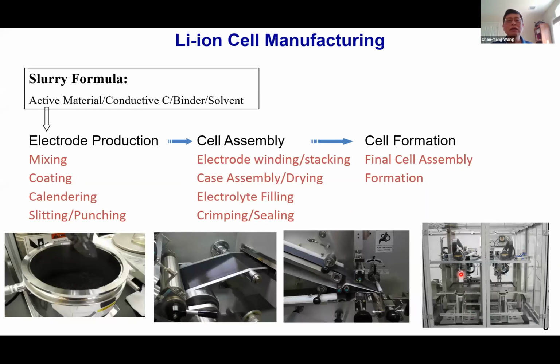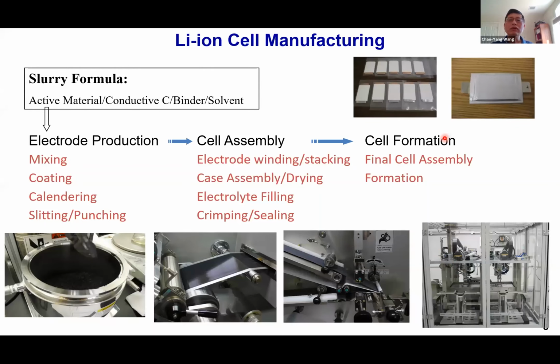So this is a stacking machine. Once those jelly rolls or stacked electrodes are made, as shown in the picture here, they are put into a case or a pouch. After drying and vacuum, you fill with electrolyte and seal the cell. And then basically you have a lithium-ion cell. Then you go through the last stage, cell formation. It's a series of small current and voltage processes to get the SEI layer formed and stabilized. After that, the cell is ready to use. So this is a very quick review of how a lithium-ion cell is manufactured, right?